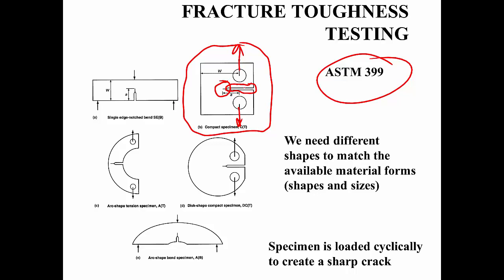And so we want to make sure that we have a crack that is atomistically sharp. And the way we do this is that we take the machined specimen and then we do fatigue on it. That is a rather small load that will not make it break, but it will create an initial crack at the tip of this notch. And once that crack is being observed externally, then the specimen is ready to be tested. And because the size of this small crack is smaller than the size of the slot, the accuracy of measuring the distance from the load to the tip of the crack is not lost by the details of that atomistically sharp crack that is required to be formed. So that is really the specimen preparation.